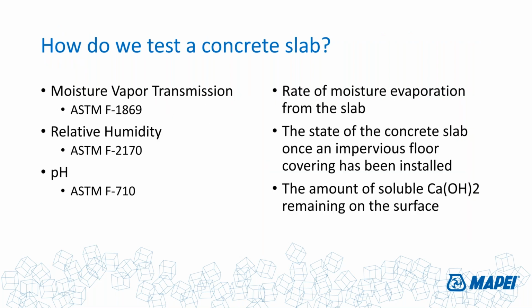Okay, but that's important to know. So summarizing what this stuff is, and we're going to get into the science here in a minute. Hopefully this has been science and not mythology. Just to confirm, again, the moisture vapor transmission rate generates results that are the rate of moisture evaporation from the slab. And keep in mind that there is a lot of water in a concrete slab over an area of 1,000 square feet. That's going to take a long time to totally evaporate. So that 25-pound number should really tell you, wow, there's a lot of water in here. Even if it's 12 or 8, do the math, go back to that 6,000 pounds of water remaining. And if it's an 8-pound concrete slab, I can't even do it, 720 days before it gets dry. Sorry, my math is gone.